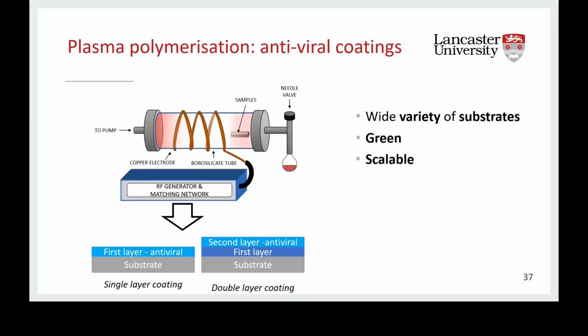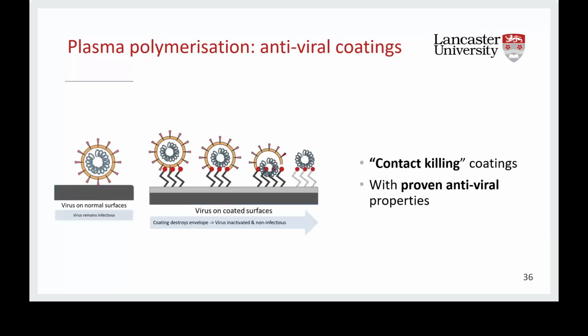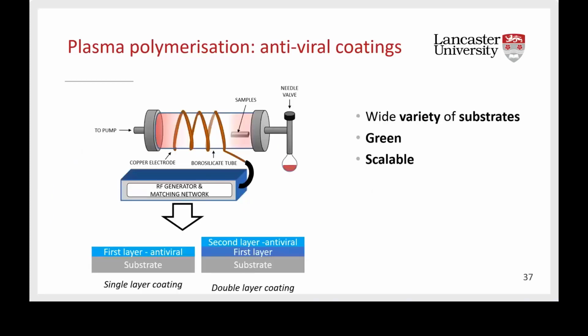So in our research group, we prepared some antiviral contact-killing coatings using well-proven antiviral molecules. The idea is that they should kill COVID once it reaches the surface. Again, to prepare them, we used plasma polymerization because we can coat a wide variety of substrates. All our tests have been performed on silicon and glass, but in principle, we can coat plastic or paper or tissue, whatever, with the same molecule. Also, plasma polymerization is scalable, so you can scale up the coating by increasing the dimension of the reactor. And finally, it is a green technique, so it is inherently energy and material efficient.